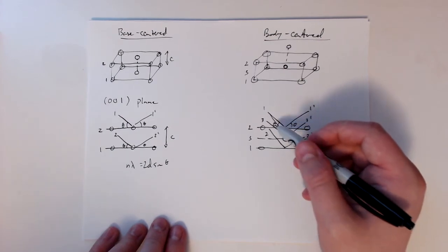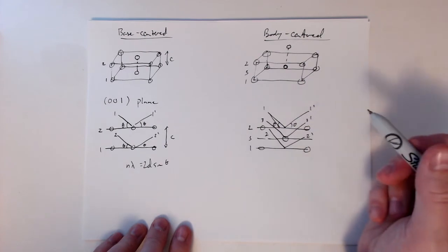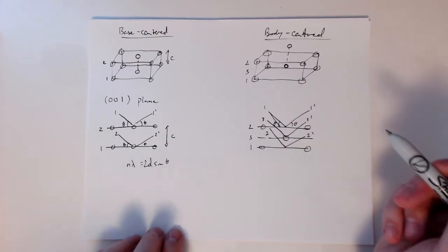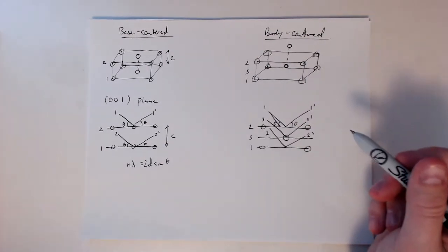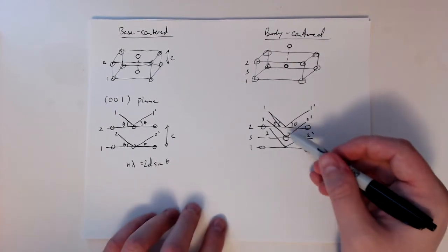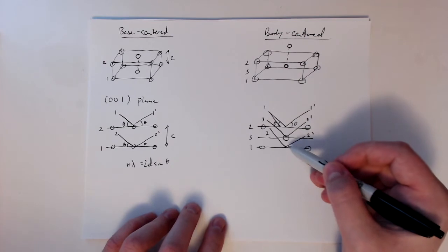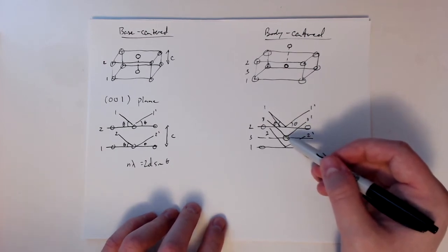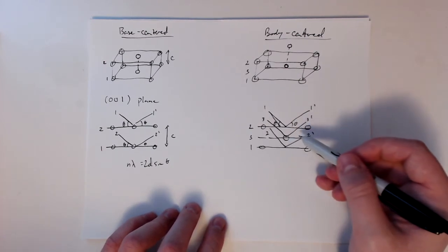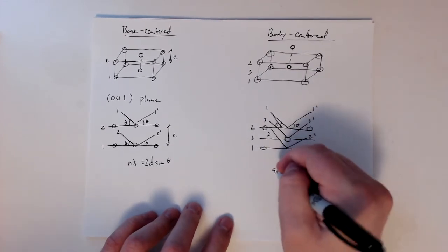But we now have a third beam halfway in the middle. And so it's basically completely canceling out what we see in those two cases, right? So for every 1 and 2, we're going to have an atom in the midplane there that's going to perfectly cancel out, or what we call annihilate.